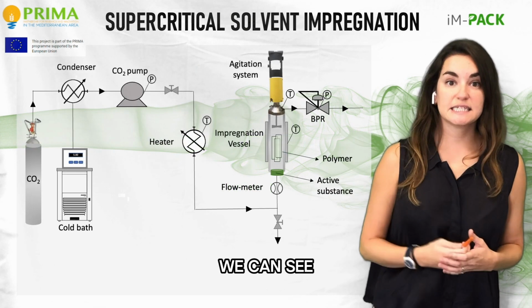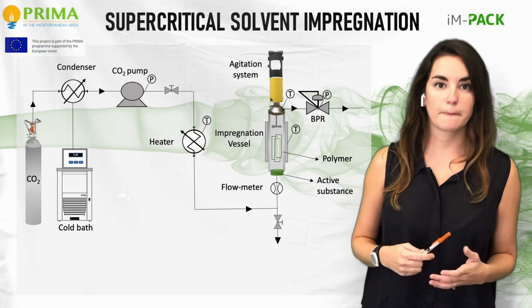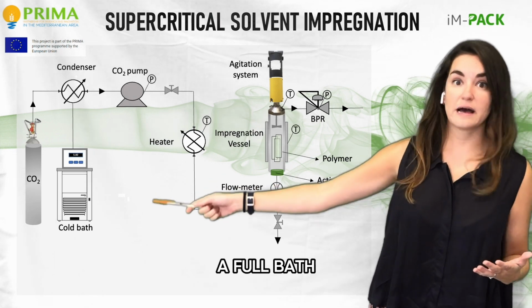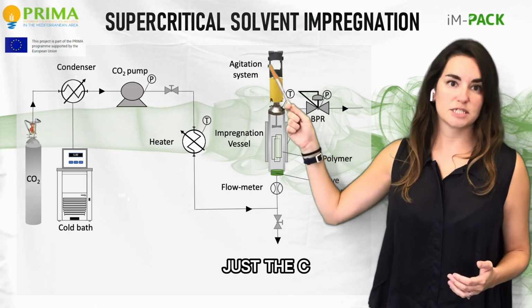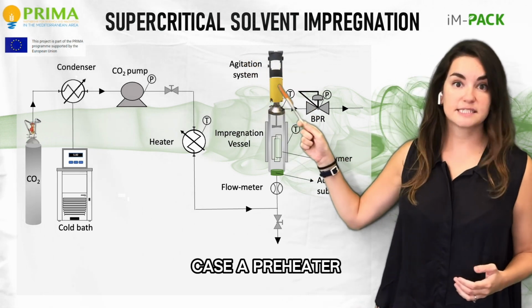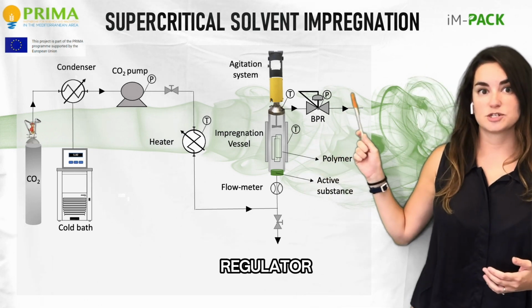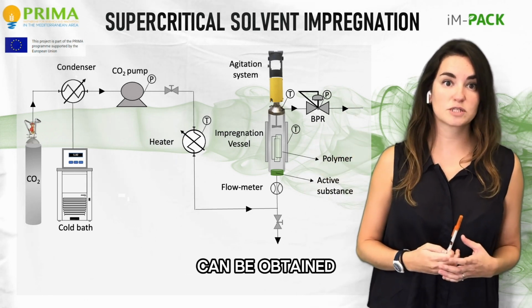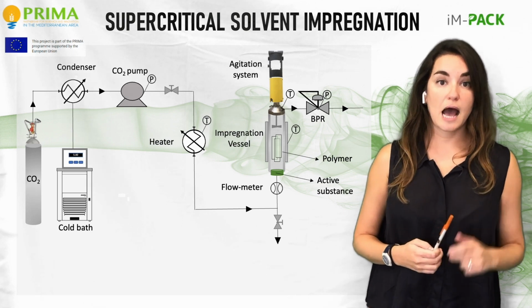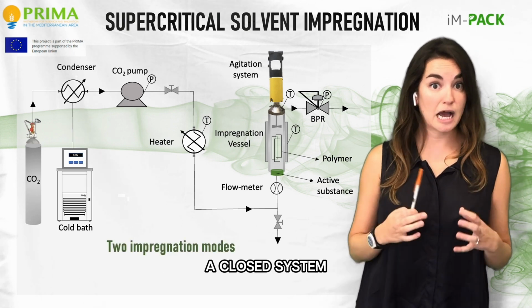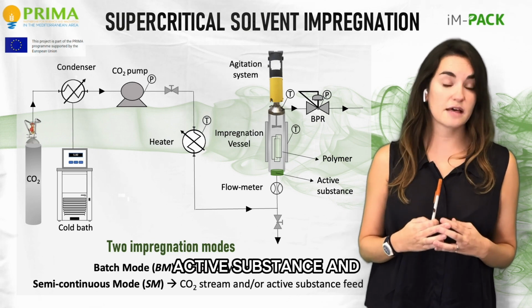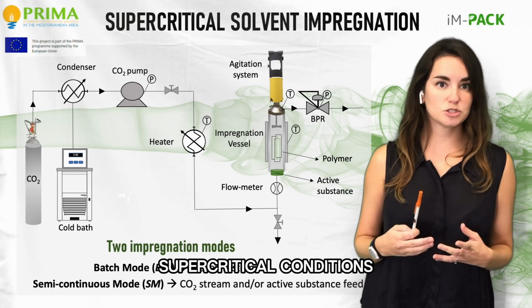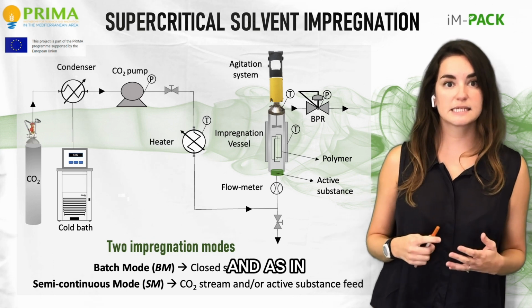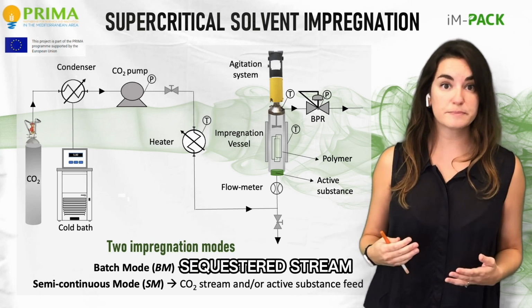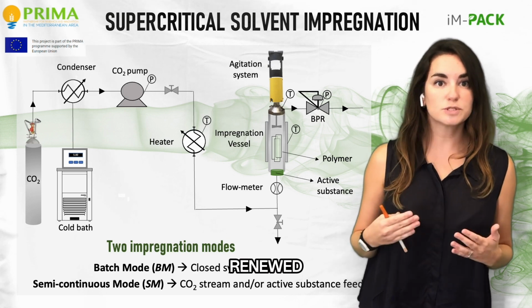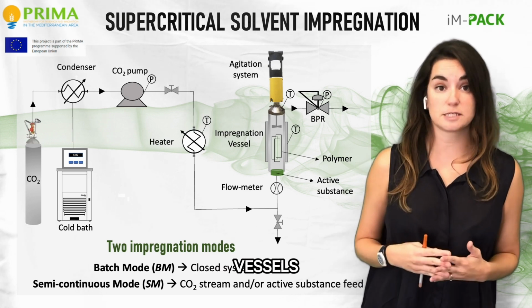On the screen, we can see the flowchart of the supercritical solvent impregnation. As any supercritical device, it has a cool bath, a condenser, a pump, just the CO2 pump in this case, a preheater, a vessel, and a back pressure regulator. The impregnation process can be carried out in two modes. A batch mode, in which the impregnation vessel is a closed system that contains the active substance and the polymer that are in supercritical conditions for a period of time, and a semi-continuous mode, in which the CO2 stream and/or the active substance is renewed into the system either by using one or two vessels.